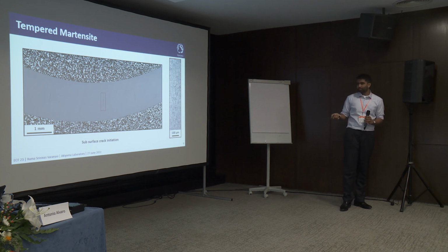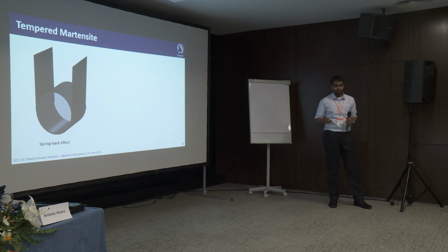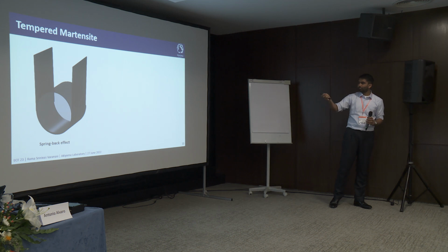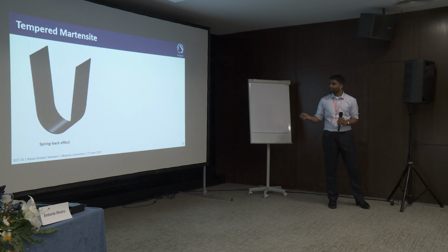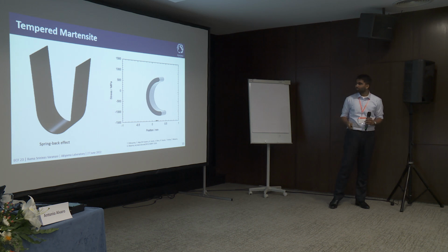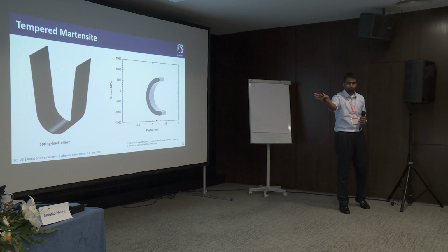The reason for subsurface crack initiation is simple: when we have a U-bend sample, this is a 3-point bending test, this is a pin, and when it is relaxed, there is a compressive stress at the surface. And this is finite element simulation of tempered martensite. -1 corresponds to the top of the U-bend sample and plus corresponds to the bottom.